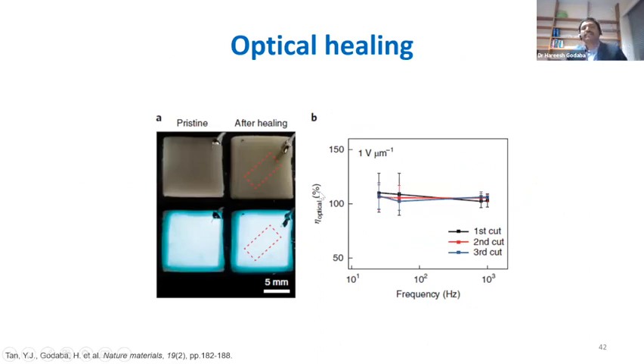Yeah, and then this basically shows the optical healing. So this is basically even after multiple cuts, we basically measure the intensity of light that is generated by this device before and after cut, and we see that even after multiple cuts, the optical healing is quite high. So after 3 cuts and healing, the optical intensity that's generated is still close to 100%.